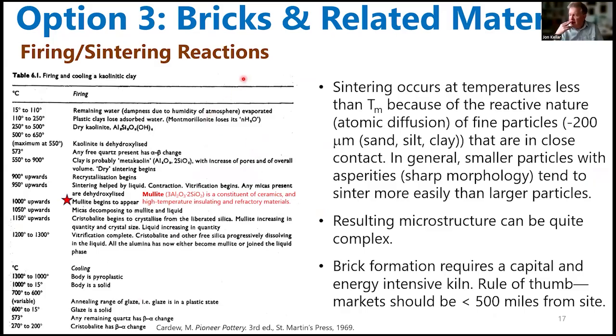A colleague of mine showed me this firing schedule, and I really like it because it goes through the temperatures and the reactivity of the minerals that are present. This is for a kaolin-based clay that includes quartz and mica. And at 1,000 degrees C, this chemical mullite begins to appear. Mullite is one of the desired constituents of ceramics because it has high insulating properties and it's very strong.